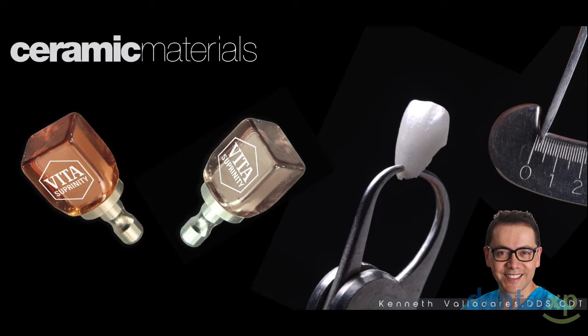It came on the market not very long ago, about 3 years ago. These are lithium silicate blocks. Not lithium disilicate. This is silicate, which has better properties than lithium disilicate, or e.max, like better color properties and strength, according to some studies. With these blocks, we can process veneers in CAD/CAM up to 0.3 millimeters thick.